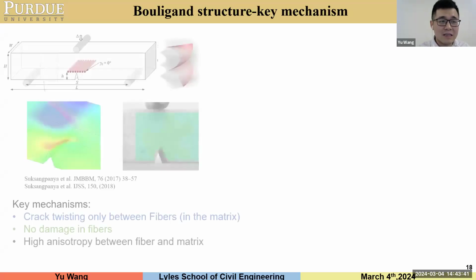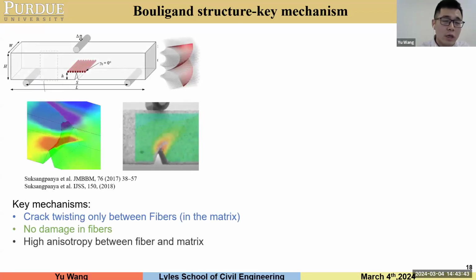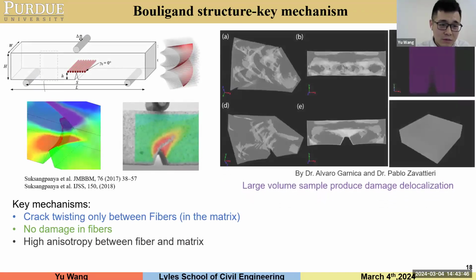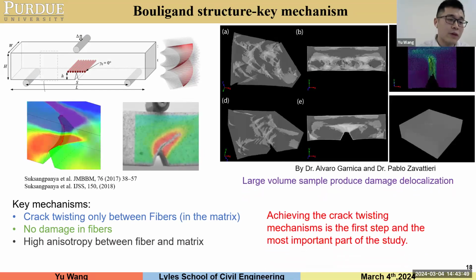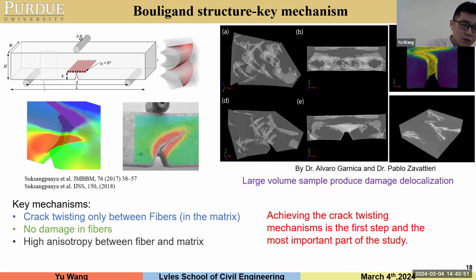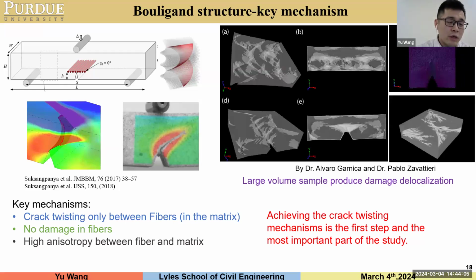To study this Bouligand architecture, there are two steps. The first step is to replicate the structure, which is relatively easy. We just need to design the toolpath. However, the second and most important part is to replicate the key mechanism of this architecture, which we can call the interfacial twist crack mechanism. In the dactyl club of the mantis shrimp, they have fiber and matrix with highly anisotropic properties, aligned with a pitch angle between each layer. So when a crack initiates, it can generate a twist crack.